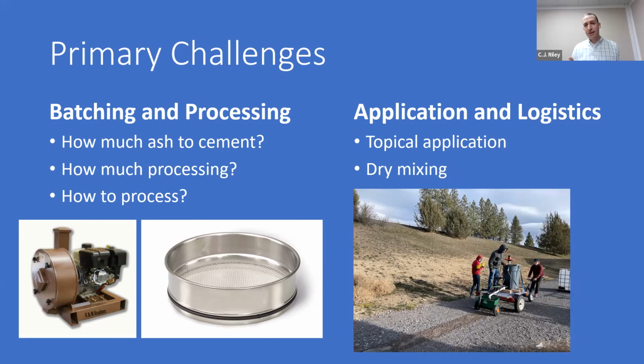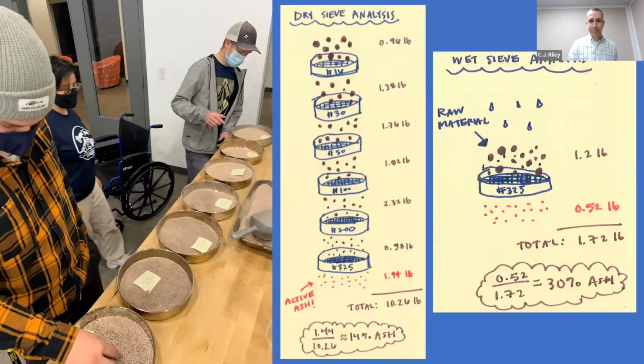The other issue we had was on application and logistics. The previous studies had suggested that topical application was going to pose a challenge. We still had some students who wanted to dig into this, and they produced this wonderful prototype of something that could mix our material into a slurry and disperse it onto the site at a precise rate that was going to be effective at letting it infiltrate into the existing ground. So they made numerous attempts at that, and we quickly realized that if we were going to apply that over a 0.2 mile trail in multiple widths along the trail, it was going to be really challenging, time consuming, and difficult to move material. So we opted for a dry mixing approach that I think worked a lot better.